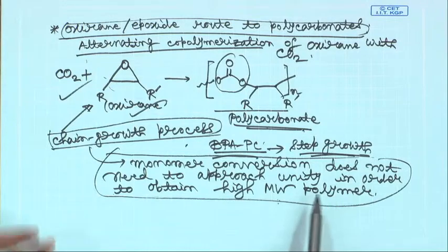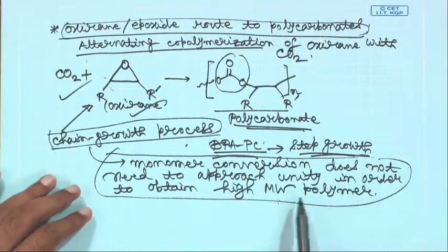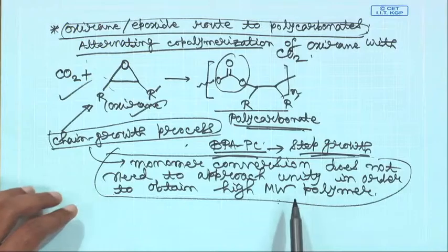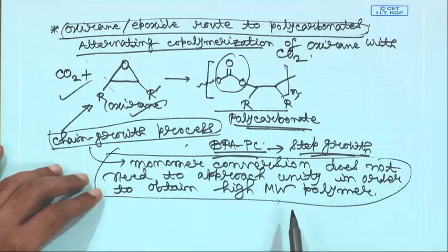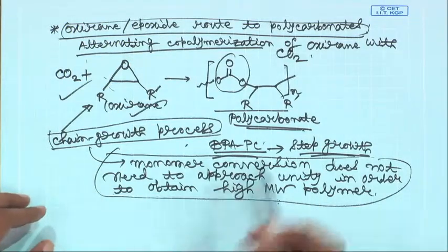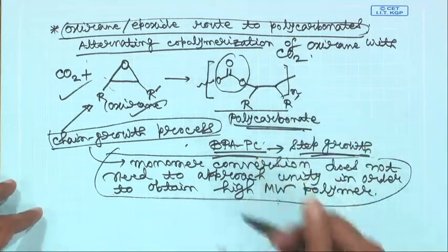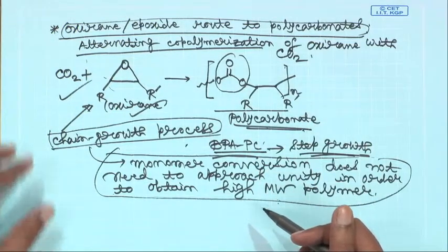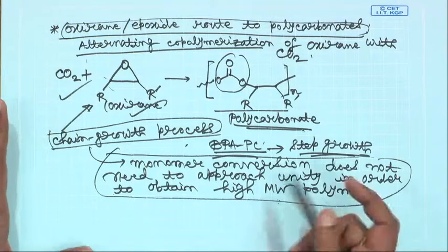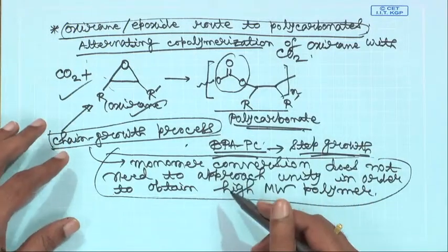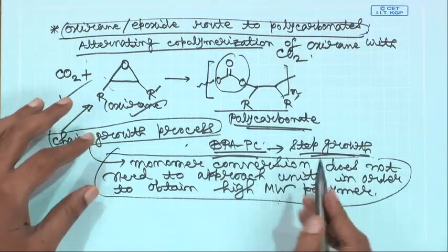Other than your typical interfacial polycondensations, where we have argued before that you will have high molecular weight quite early in the reaction, typically in step growth polymerization, say if you are looking at melt polycondensation or solution polymerization routes towards polycarbonates, your molecular weight will develop slowly.